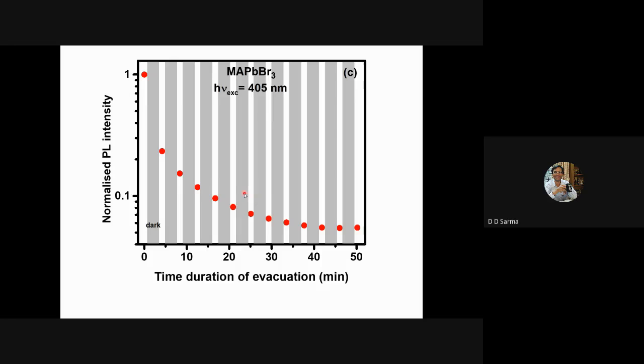Basically, what happens then, we figured, is that, remember, I have said that this sample is fantastic because it has a very good absorption coefficient. All the photons that are coming in get absorbed very close to the surface. And the surface has a lot of defects. Those defects are normally passivated by oxygen adsorption, some moisture adsorption. As soon as I start to pump, these adsorbed gases are released and they go away, and the defect states become active. These defect states quench your photoluminescence intensity, and that's why with pumping you would go down.